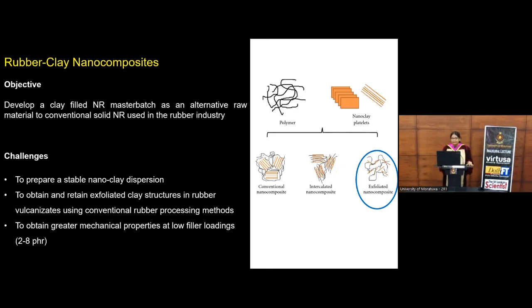If nano fillers are added in the rubber industry using conventional rubber processing equipment, conventional composites are produced. The nano platelets will not be separated to give enhanced properties. Intercalated or exfoliated structures can be produced, but the main challenge is to obtain the exfoliated structure in the master batch and to retain this exfoliation when compounding with other ingredients using high energy intensive rubber processing equipment. Another challenge is to obtain greater mechanical properties at low nano clay loadings.